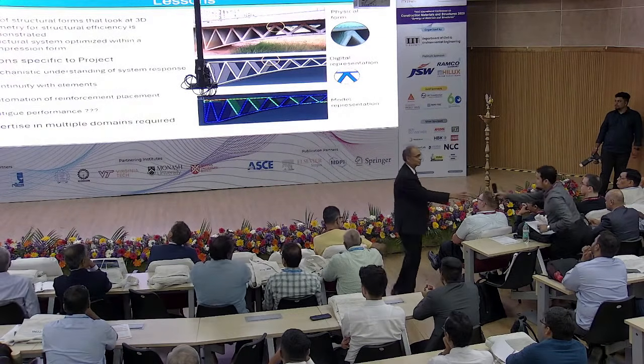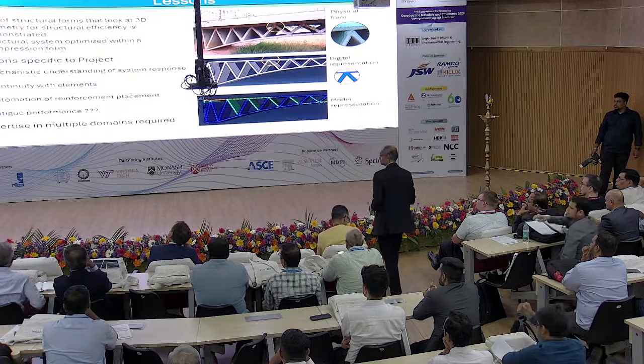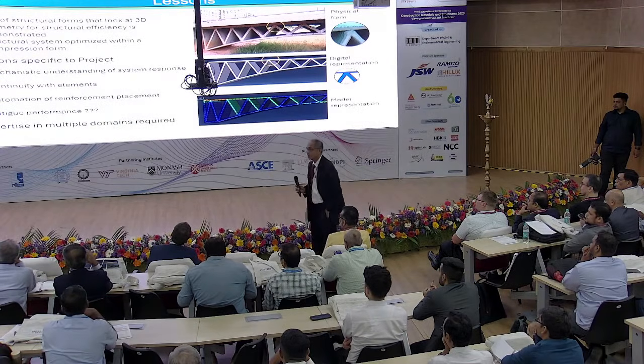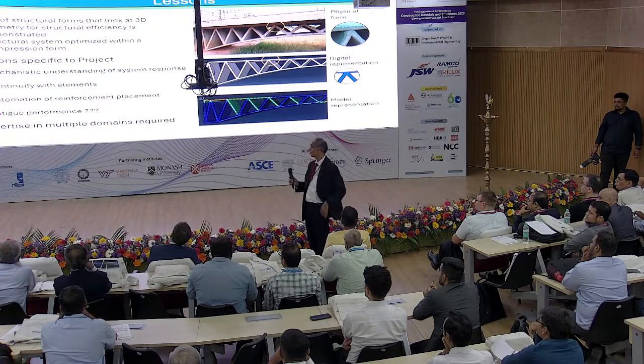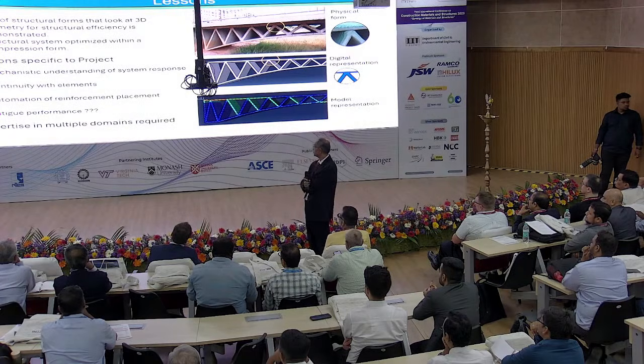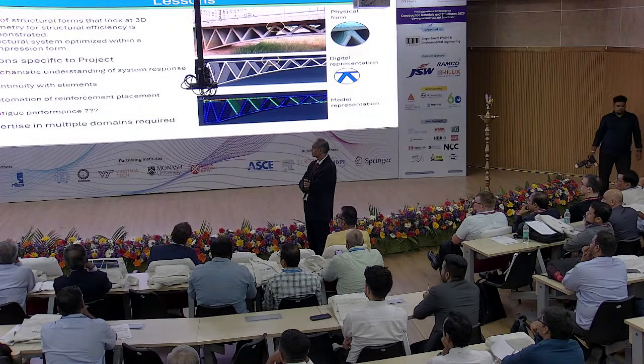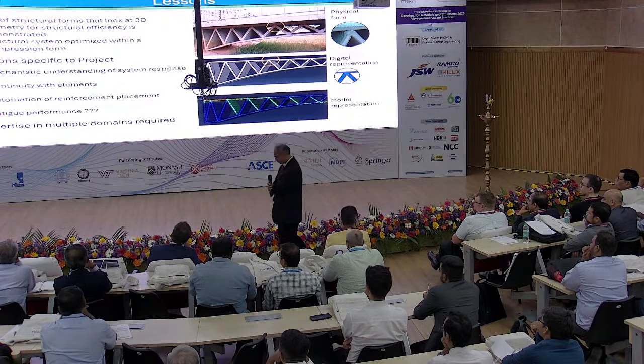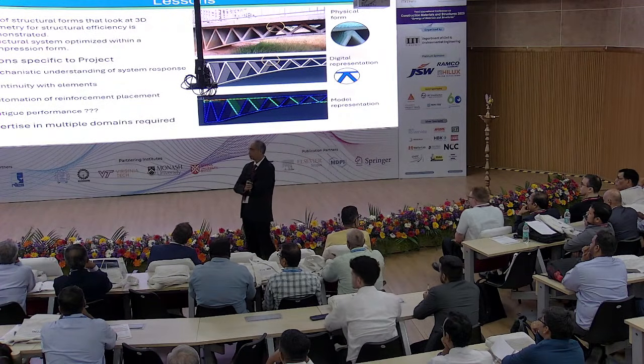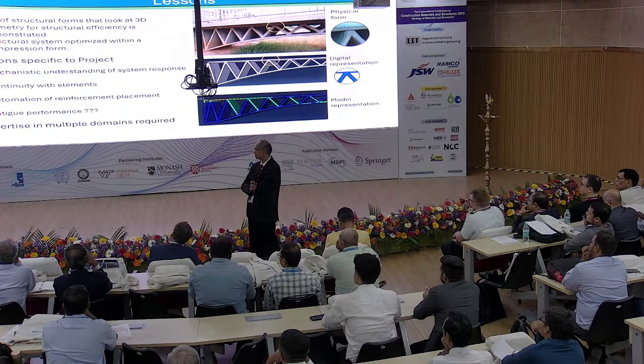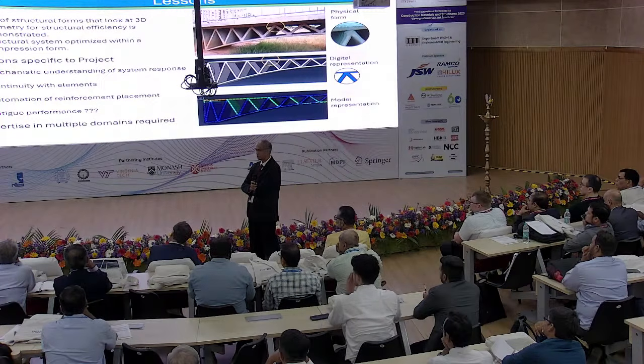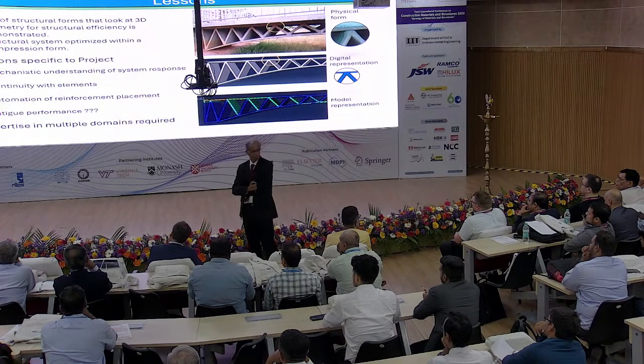No, that's a very legitimate concern, and what we did was, if you look at the circle at the very top, you see the top filament, and then you see the lattice, the diagonal lattice members, right? Now, during printing, depending on the precision you get, the contact between the members varies. So, you really have to get your printing done properly, where the precision at that particular joint becomes very important.